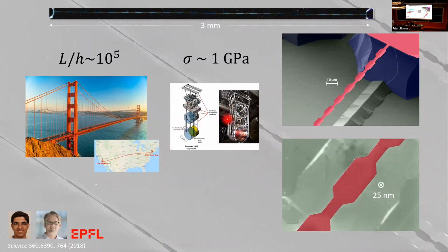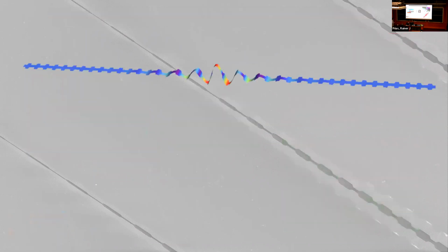The reason they do that is if you're trying to make a really high performance vibration isolation system, you start to worry about the violin modes of the suspension springs. And LIGO really wanted to load their suspensions to near the yield stress to push the violin mode frequencies outside of their detection band. This also actually gives rise to an effect called dissipation dilution, which makes the Q factor of those vibrational modes really high. And it's that effect that we're leveraging to get these really high Q nanomechanical resonators. I'll talk a lot about that in the middle of this talk.